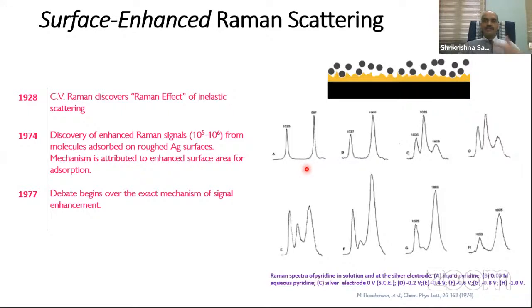But when they made this rough surface, they saw that certain peaks appear which belong to pyridine. So it was a very curious thing, why the pyridine, which I otherwise would not be able to observe, I can observe whenever the surface of the silver electrode is rough. And then in 1977, a lot of debate started.